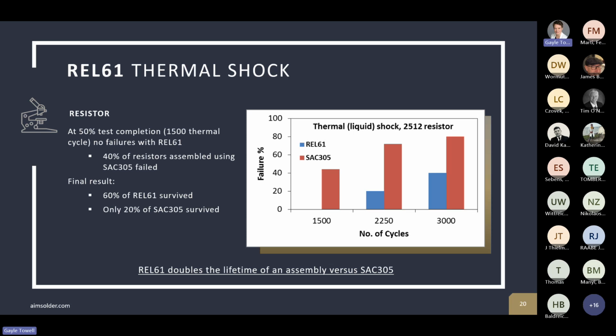So with thermal shock testing, here we are looking at a resistor component. So with thermal shock, we change the temperature more rapidly. And with REL61 compared to SAC305, we see after 1,500 cycles, REL61 has no failures, whereas SAC305 is above 40% failure rate. The end result after 3,000 cycles, 60% of the REL61 joints survived, only 20% of the SAC305 joints did. So we had almost double the lifetime of an assembly compared to SAC305.